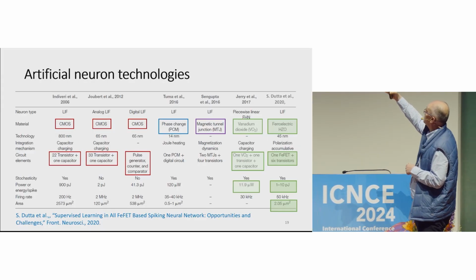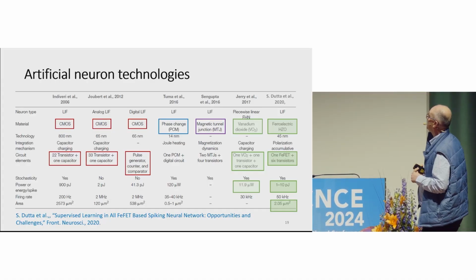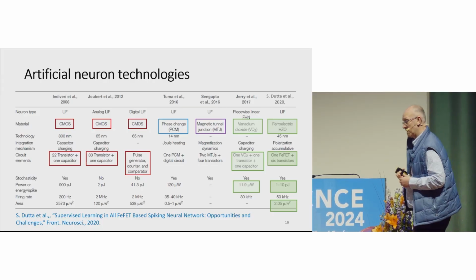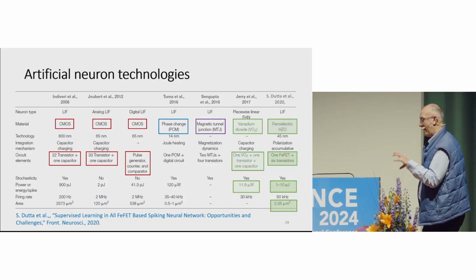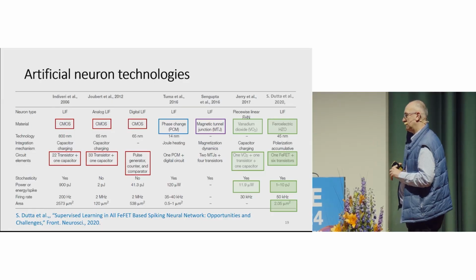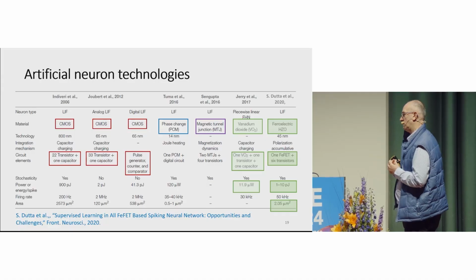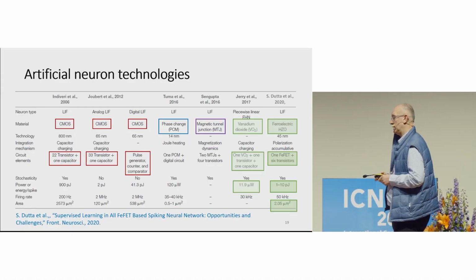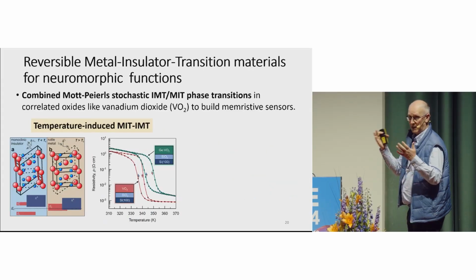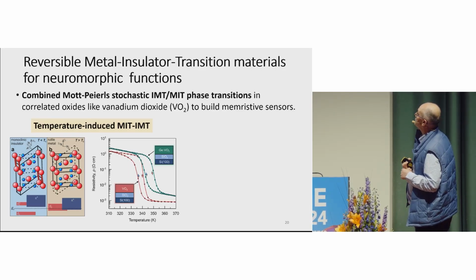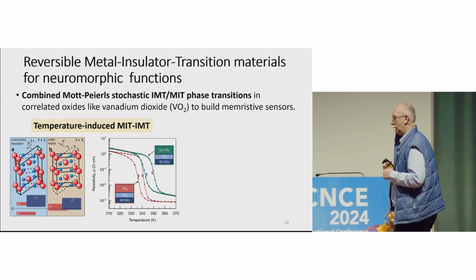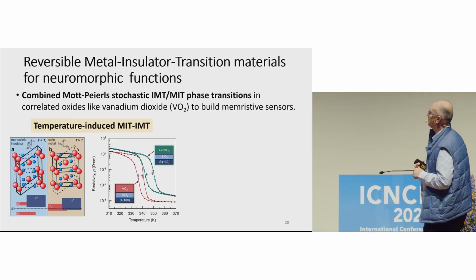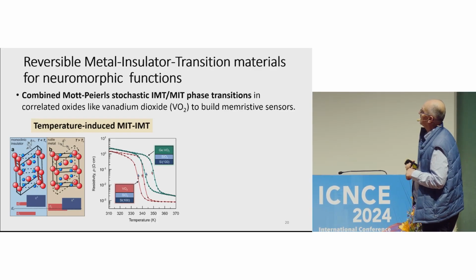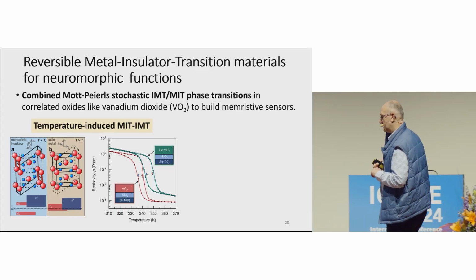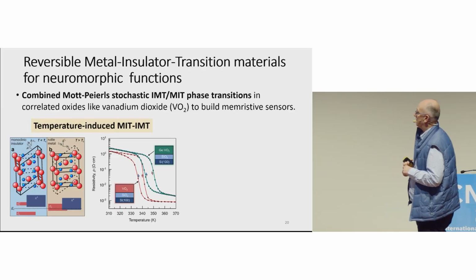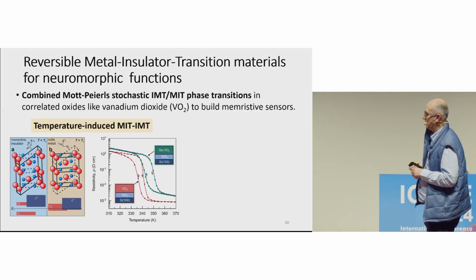But what is very interesting is, when you see the role of emerging technology, phase change, magnetic tunnel junction, Mott insulator like vanadium oxide, ferroelectric material, all this can be used now to have a particular device that has a memristive behavior to build, maybe even with 2-3 transistors around, an oscillator that behaves as a neuron and is tunable, and it can reproduce the characteristics that we need for computation. So I will show you one example in which a reversible metal insulator transition material can be exploited in order to build such a neuron. There is a long debate in vanadium oxide about the mechanism that explains this transition between the insulating state and the metal state that happens around 68 degrees C.